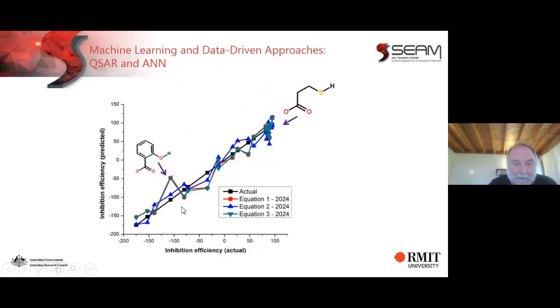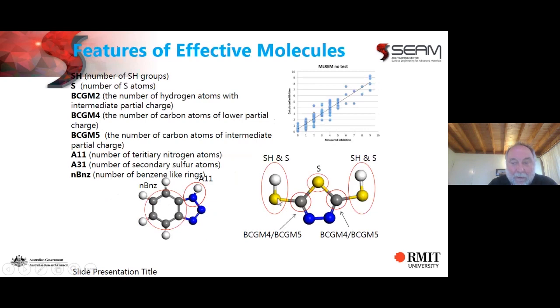And this is an example of the output from one of those models, the inhibition efficiency actual against the predicted one, using that combination of DFT derived parameters and SMILES derived molecular features. And we did obtain quite good models. And as we mentioned before, it tended to depend on whether there was a thiol group, a sulfur group, an oxygen group.